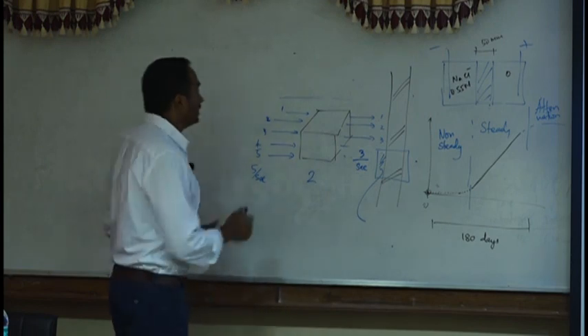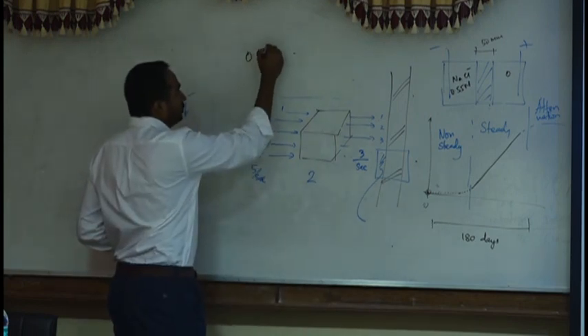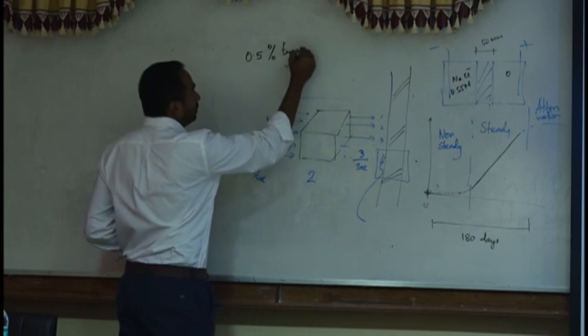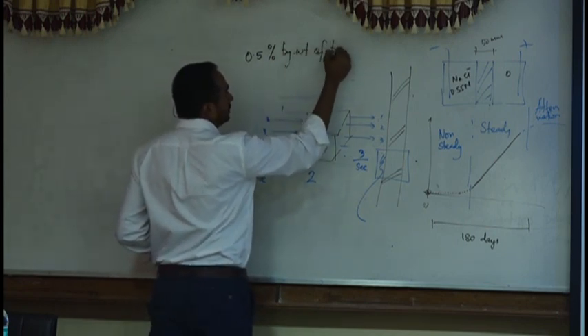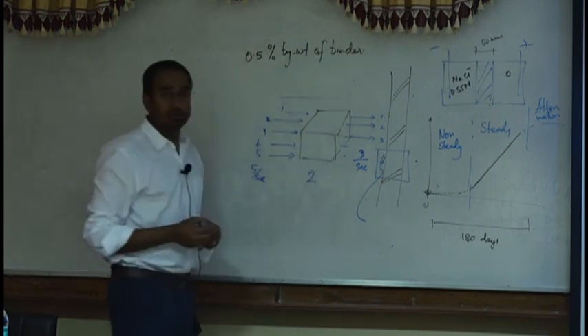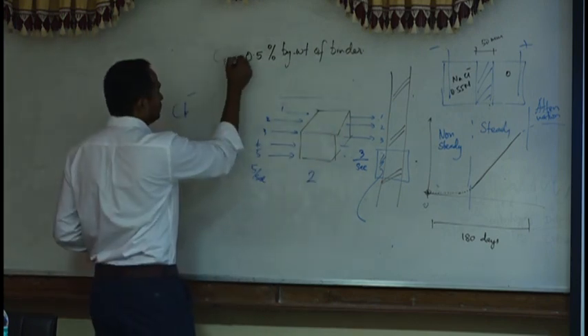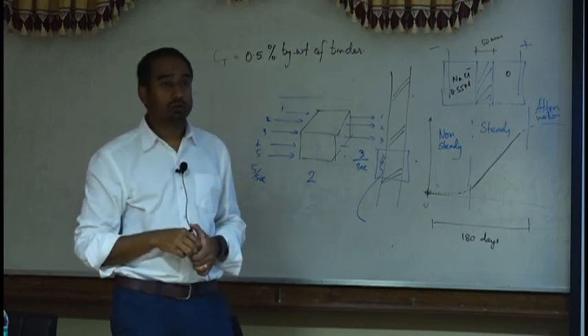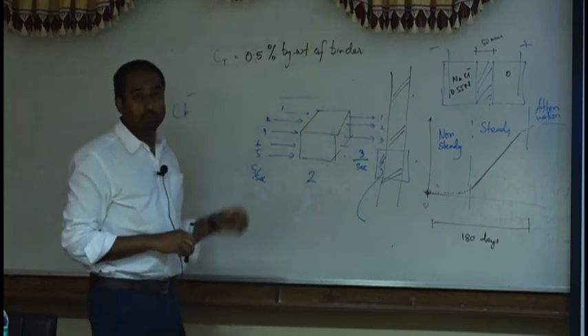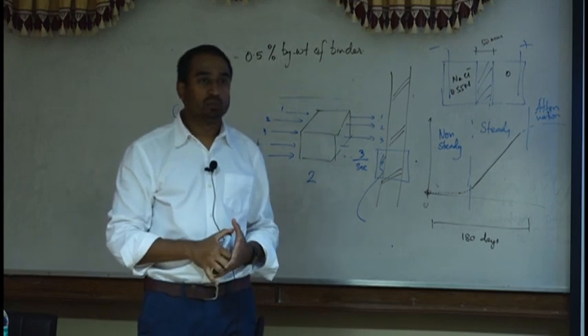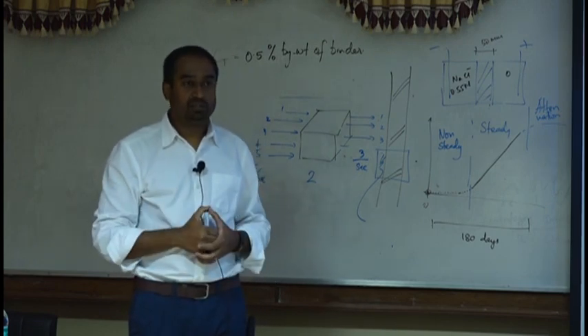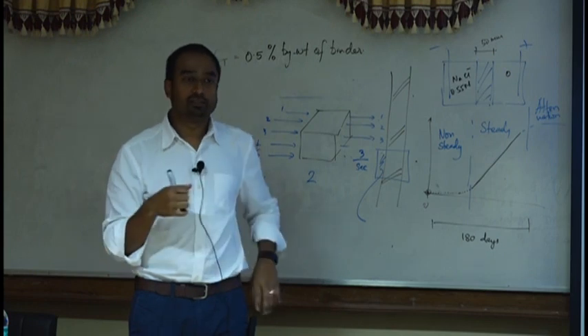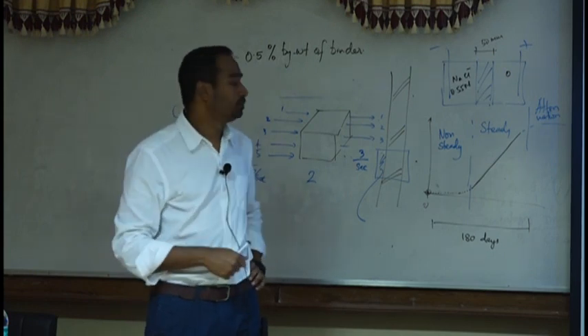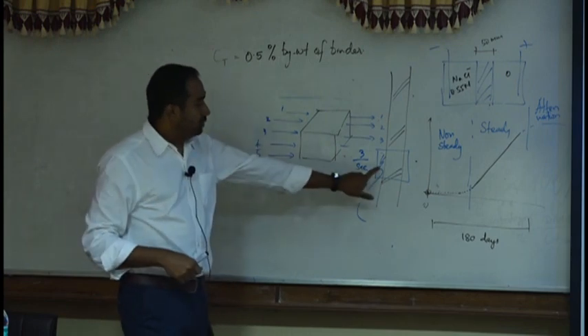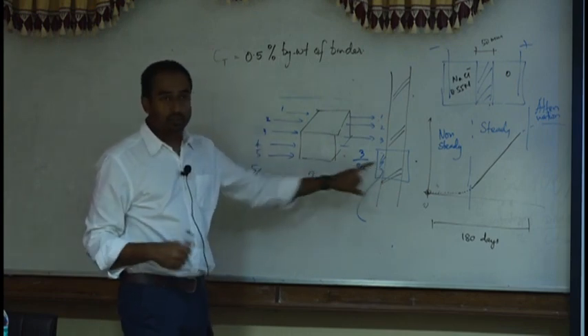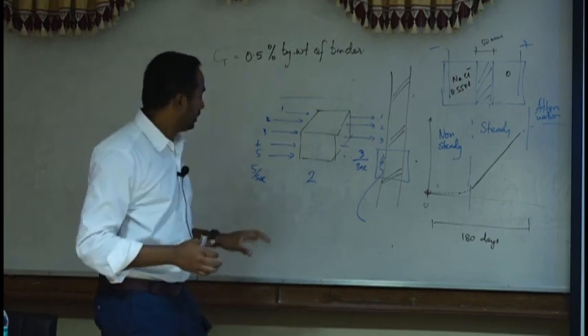But what we know, most standards would say 0.5% by weight of binder can be taken as the chloride threshold. We have seen concrete corroding with 0.2. We've also seen concrete not corroding for nearly 1. It depends on other factors. Clearly it depends on the pH as well. So threshold refers to the chloride at the interface. So it's the accumulated chlorides that are coming in.